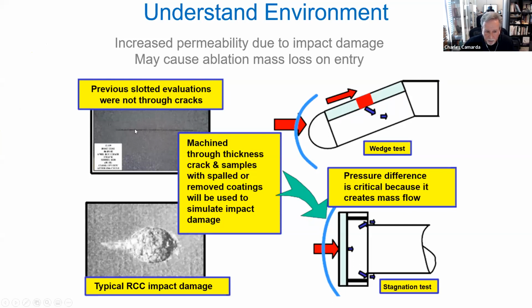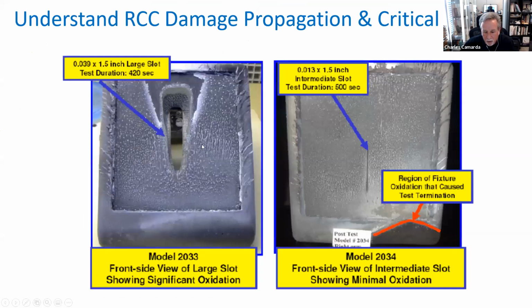We're now damaging those small coupons with slits, with impact damage, and we're trying to understand how that damaged material will now react and respond after 10 to 15 minutes in a very high temperature flow. Here the flow is from the bottom up, and you notice a small slit grows, and you notice that the downstream lip, since the flow is from the bottom to the top, gets much hotter, and so instead of growing symmetrically, it grows like a wedge.